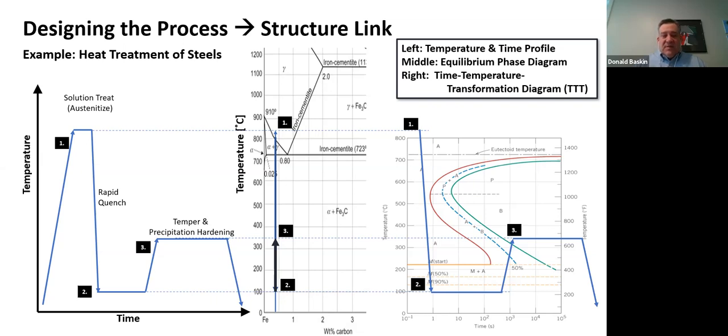This martensitic material is oftentimes too brittle to be used in structural applications. If you made a bicycle out of pure martensitic steel that hadn't been tempered, you could hit a bump and the chainstay or some other tube might snap and then you'd be in trouble. The tempering stage is very important. Typically when you temper a low carbon, inexpensive steel, you'll get tempered martensite. The martensite has these needle-like structures, and they'll grow a little bit, so they're a little bit less coarse and a little bit more pliable, let's say. It's a little bit easier to get a crack or dislocation through there, so the material is tougher. You might lose a little bit of strength, but you'll gain enough toughness or energy absorption capability that you can then use this material in a practical application.